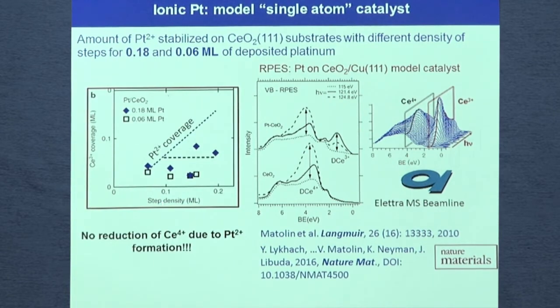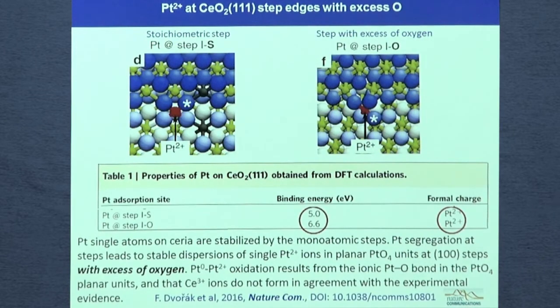And again, if we are changing the density of steps, we are checking the cerium 3+ concentration. This picture shows that in the normal situation, the platinum is reducing cerium oxide due to the charge transfer. The charge transfer, there is a paper also from this year, which we have published, showing the charge transfer between platinum and cerium oxide. And we can show that there is in fact practically no reduction of ceria, which is surprising, more or less.